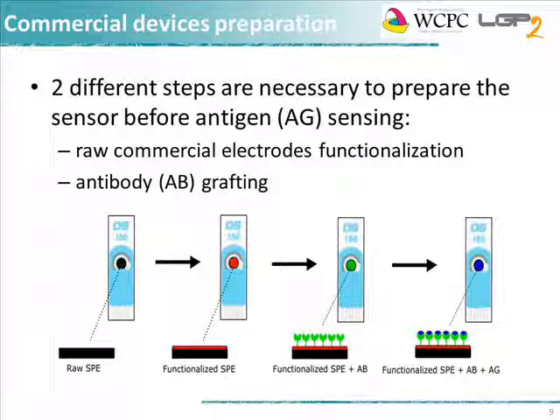The carbon-based raw material of the working electrode is first functionalized in order to enable later the grafting of the antibody. Different functionalization agents were used, displaying functional groups such as amine or carboxylic groups. They are called A, B, and C in the studies because the structure is still confidential. After functionalization, the antibody is then grafted on top of the working electrode. The sensor is now ready for antigen sensing.